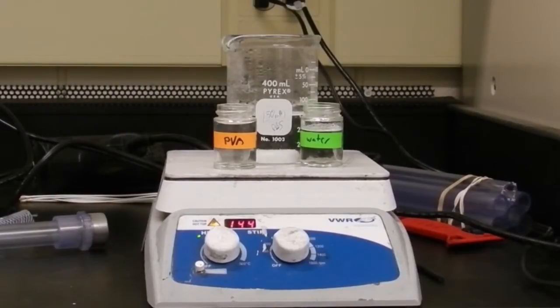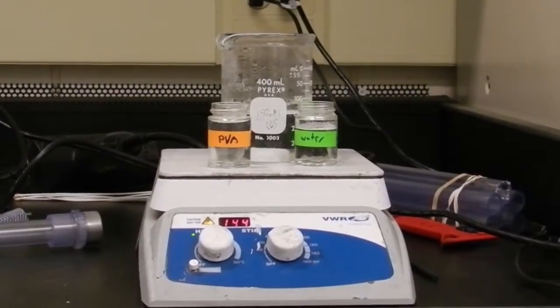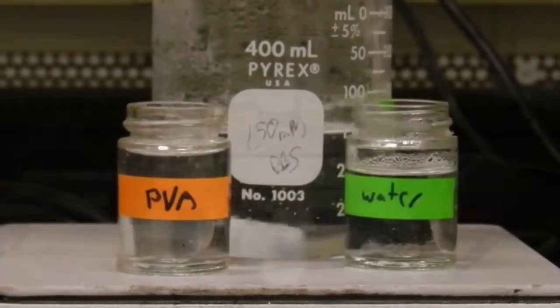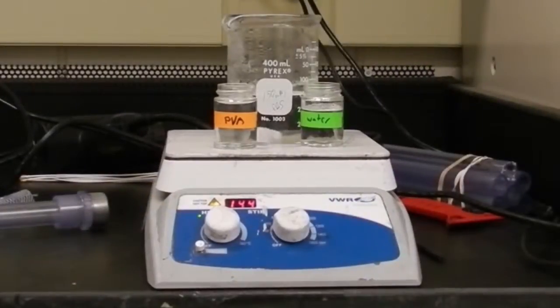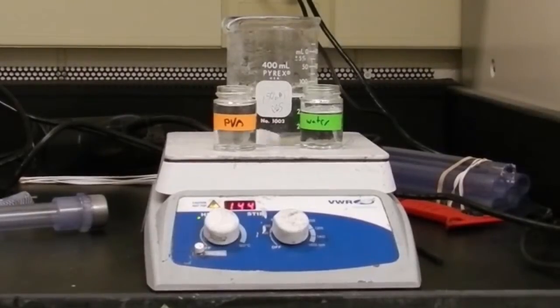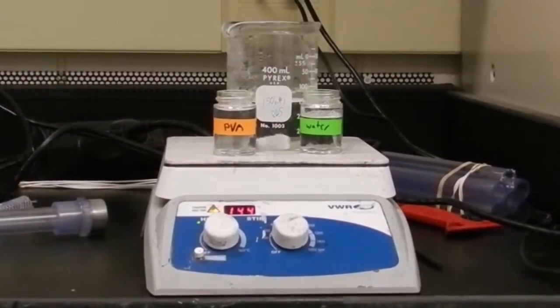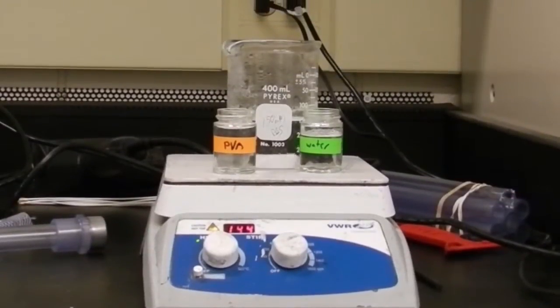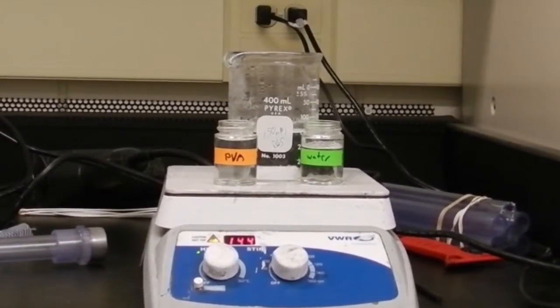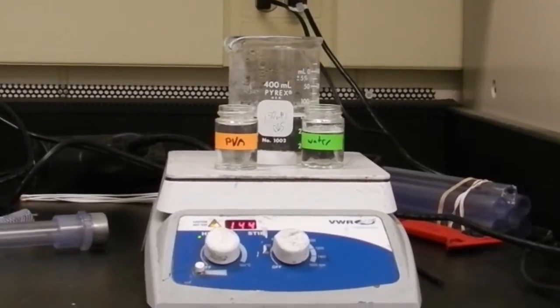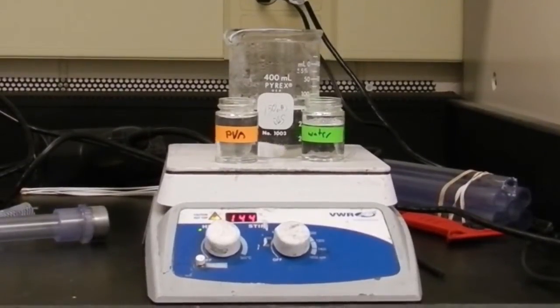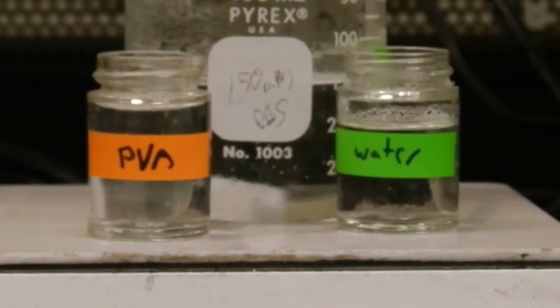The water I have there to clean out the air gun in between layers, because it will take several layers on the cathode in order to completely cover it. If you're going to have your anode directly next to each other and you need the PVA to provide a barrier between the two, then you'll probably need to do six or seven layers of the spray-on application.